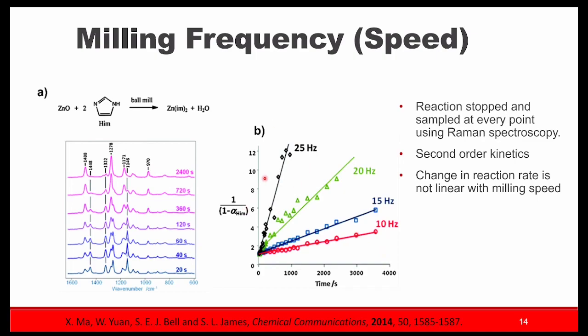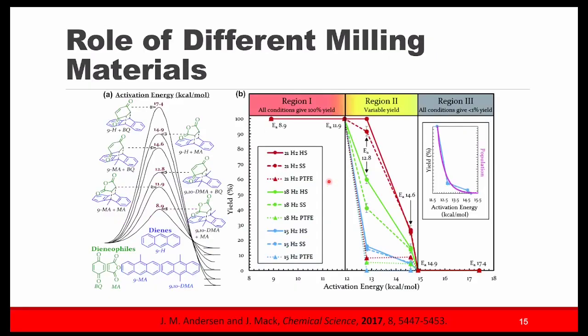And what's interesting there, they stop this reaction after a certain amount of time, and they take the sample out and analyze it using Raman spectroscopy, and you get these second order kinetics. And what you see is that the change in reaction rate is really not linear when it comes to change in milling speed. So doubling the milling speed does not double the reaction rate. And this isn't super surprising, but this was a really nice starting point. The community was starting to look at, okay, how can we get kinetics and use this data to better understand how mechanochemistry works? This is one of my favorite papers.